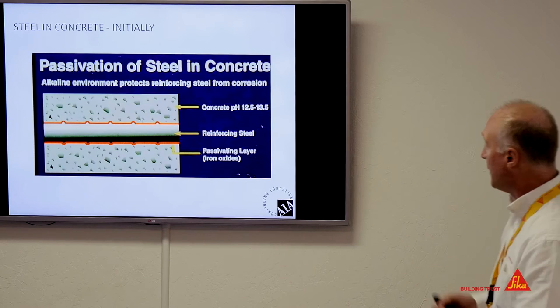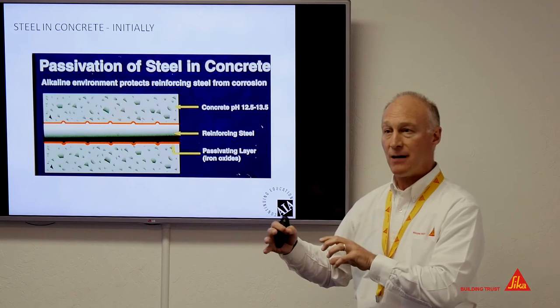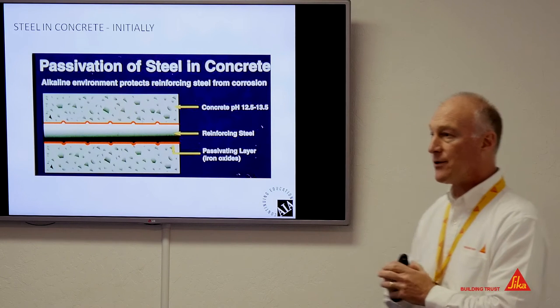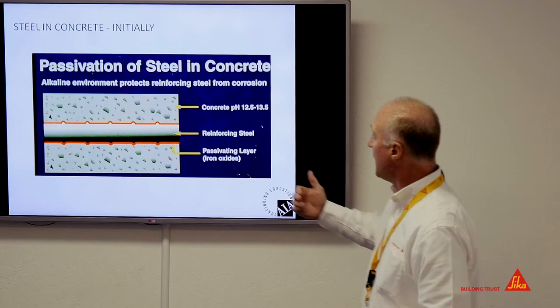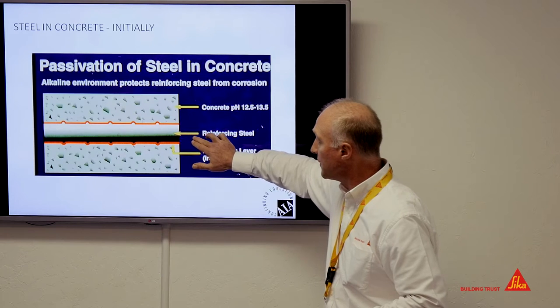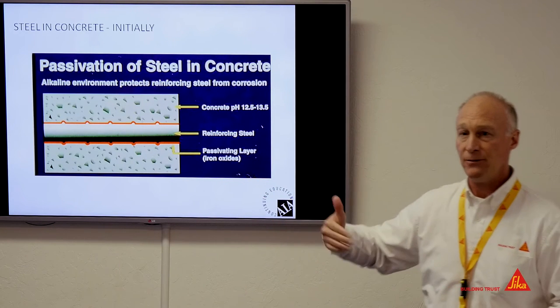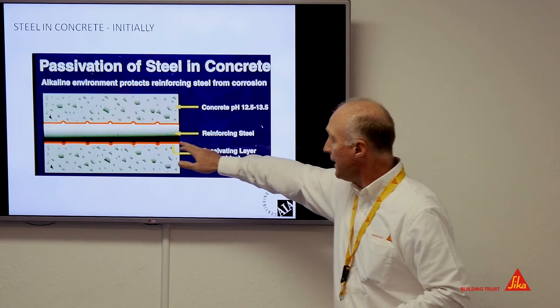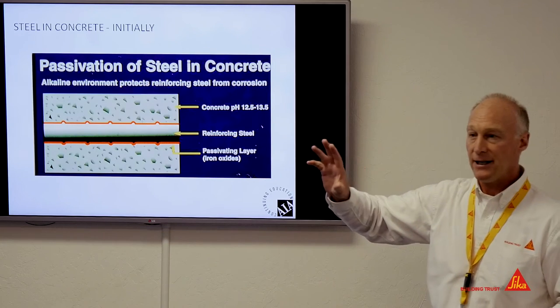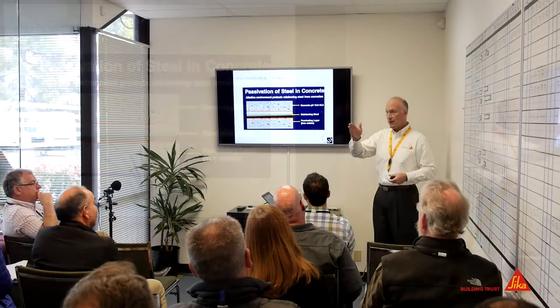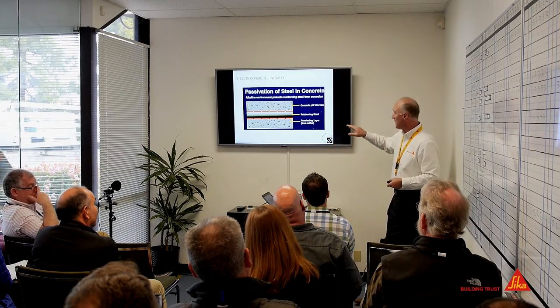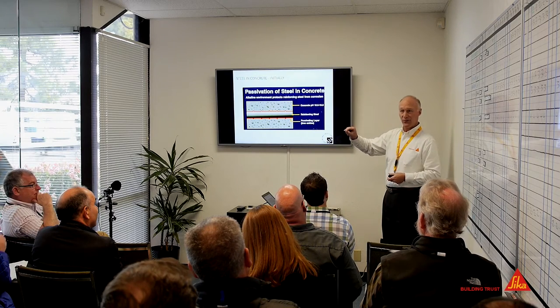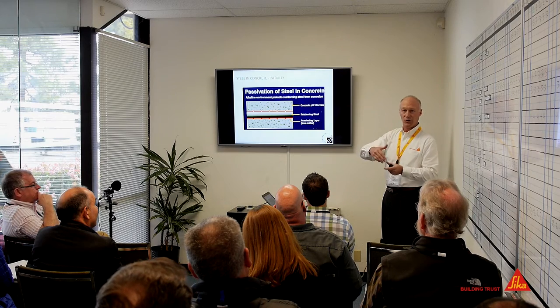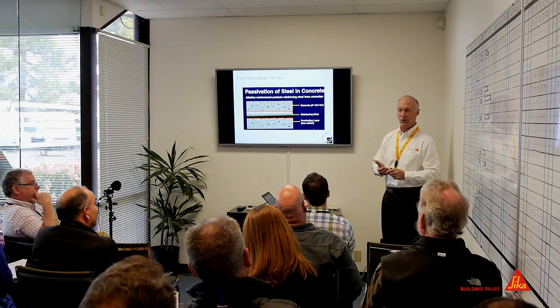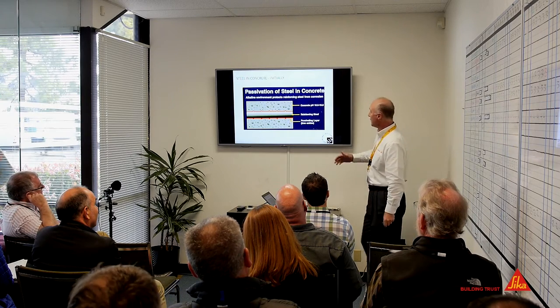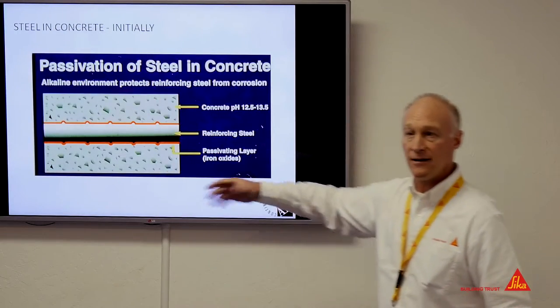I made mention of this earlier, but just to take a step back, we've seen examples of some problems, and we've been covering some of the issues that are challenges within the industry. But if we take a step back, when we first place concrete around the reinforcing steel, a passive layer will form. And this is in concrete that has a high pH. This passive layer, anybody take a guess how thick that is? If you took a human hair and divided it 10,000 times, that's the thickness of that passive film. And it's that passive film that's really protecting the steel from corroding. Once the film is destroyed, and you're in the presence of oxygen and moisture, that steel can then corrode. As I mentioned, if we have good cover and lots of it, that film will remain intact and the steel will not corrode.